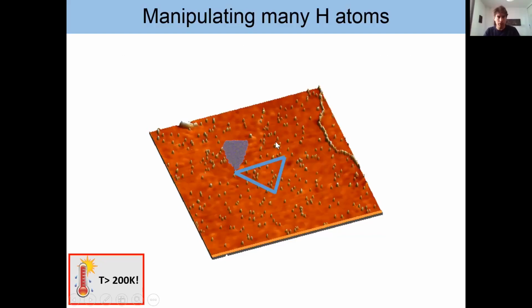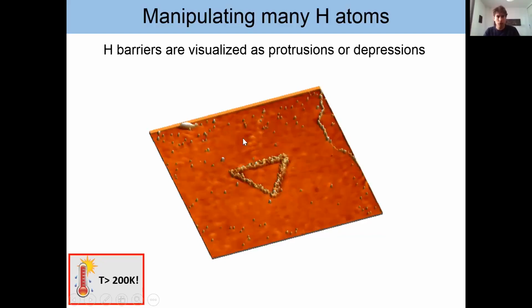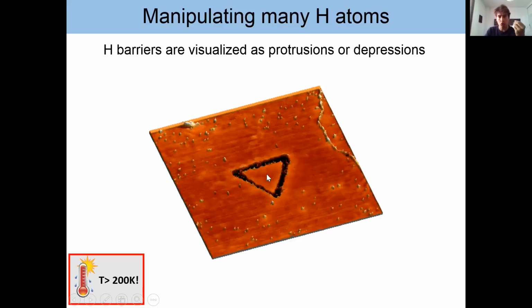And then we see that we had here the hydrogen atoms, we do the trajectory, and now we have the formation of this triangular structure. So we have hydrogen barriers. Depending on the voltage and the tunneling condition we use, those tunneling barriers can appear as protrusions or as depressions. Essentially, for low voltages, we see them as depressions. And this already is an indication that the density of states here is much lower than in the rest of graphene. It seems like we are cutting graphene.